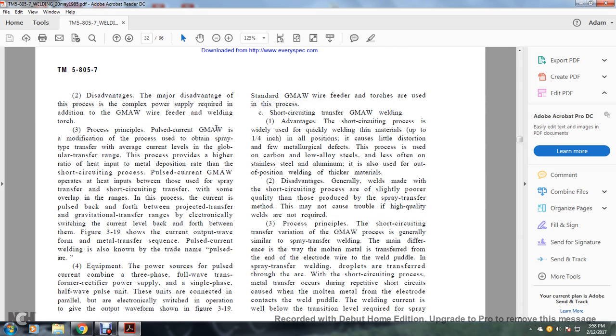Process principles. Pulse gas metal arc welding is a modification of the process, combining the spray transfer with the average current level of the globular transfer. The process provides a higher ratio of heat input to metal deposition rate than short circuit. Pulse gas metal arc welding operates with heat inputs in between the use of spray and short circuit transfer, with some overlapping range. The current is pulsed back and forth between the projected transfer and the globular transfer range, electronically switching the current level back and forth. Figure 3-19 shows the current output waveform.